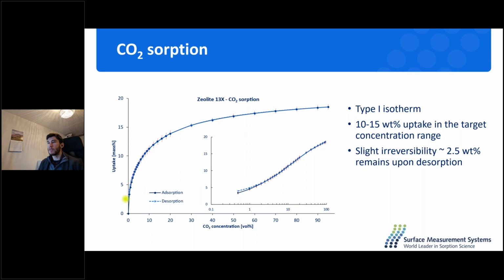There is a slight irreversibility in the CO2 sorption isotherm, which is interesting, because it means that there are either some defect sites or some CO2 that cannot be recovered. But overall, it seems like a promising material. Yeah, this 15% weight uptake is something that you would potentially use in a process.